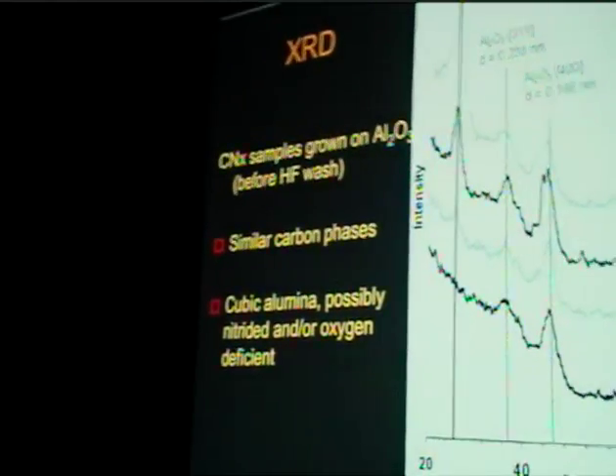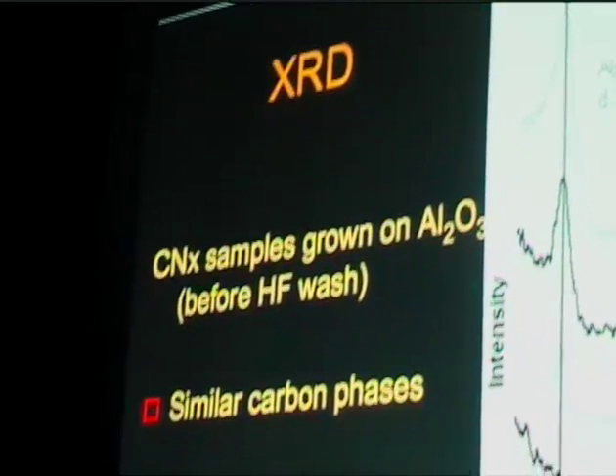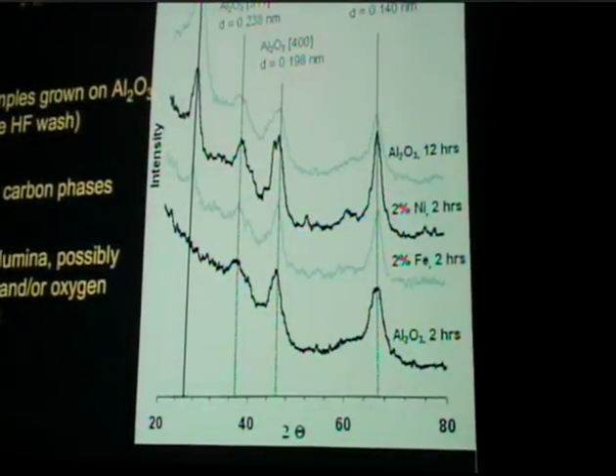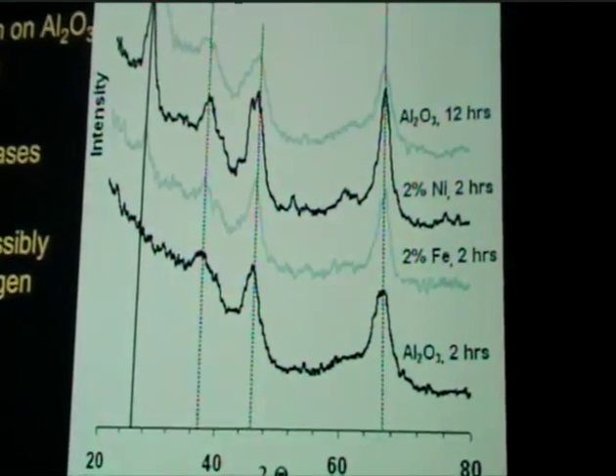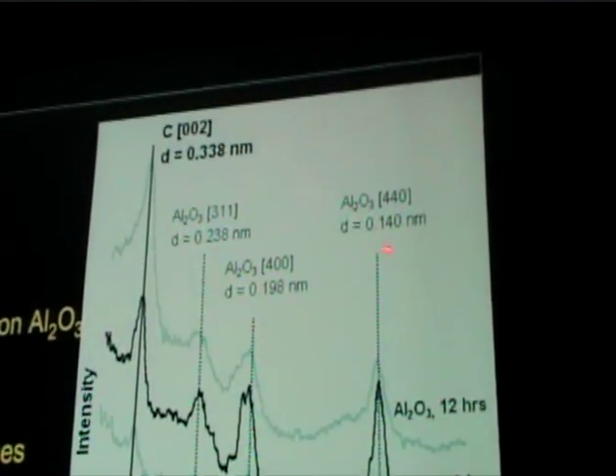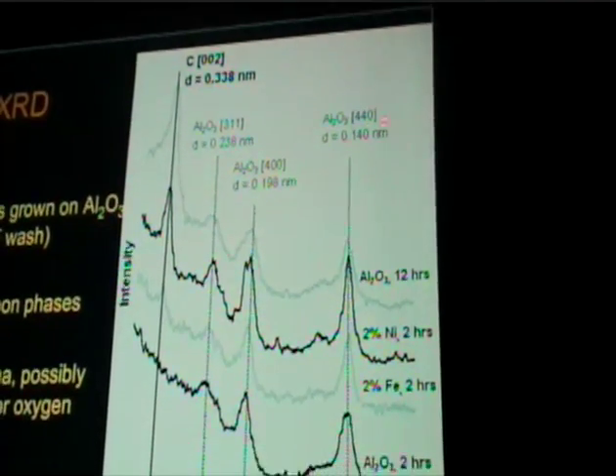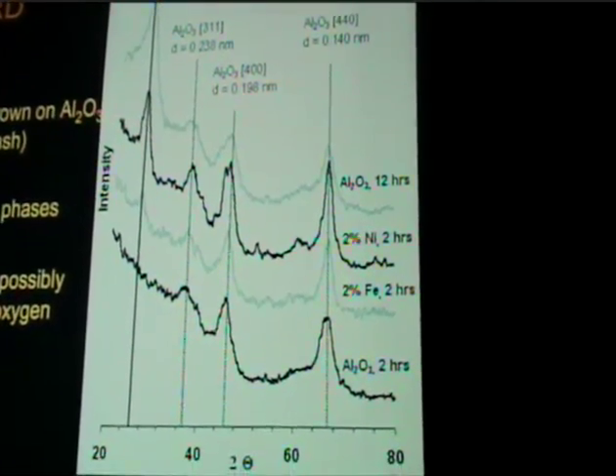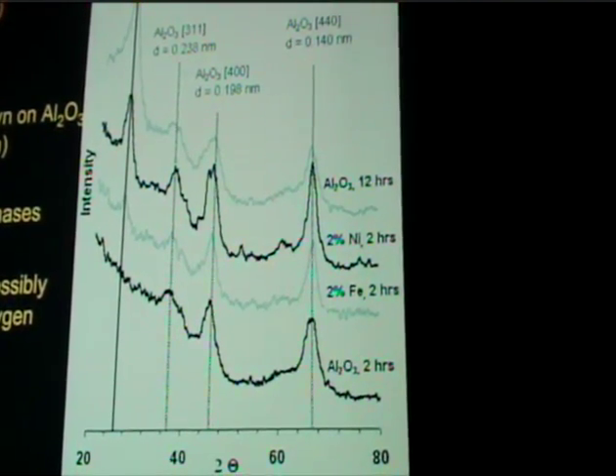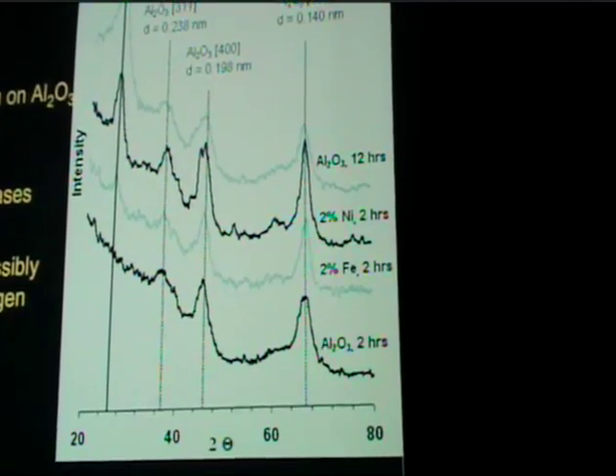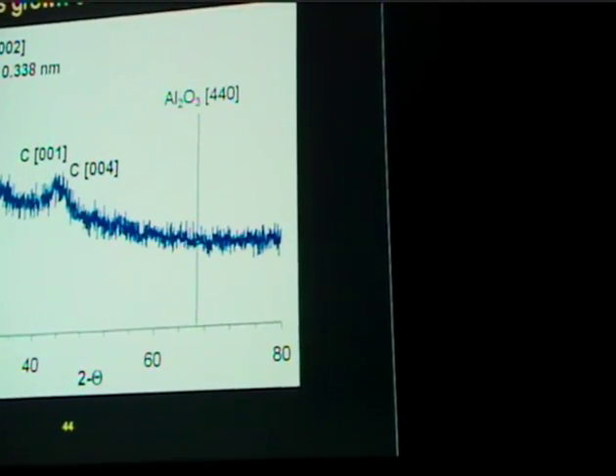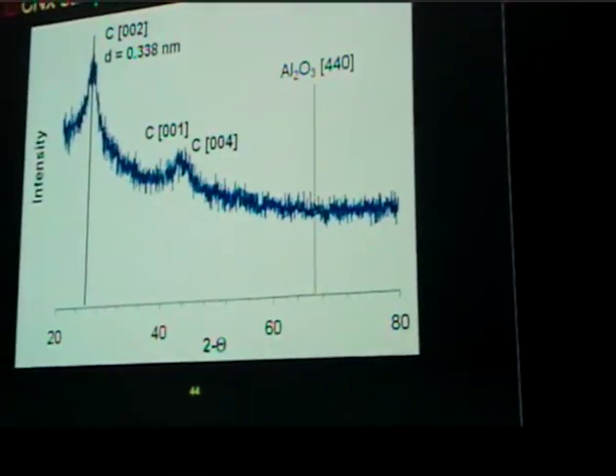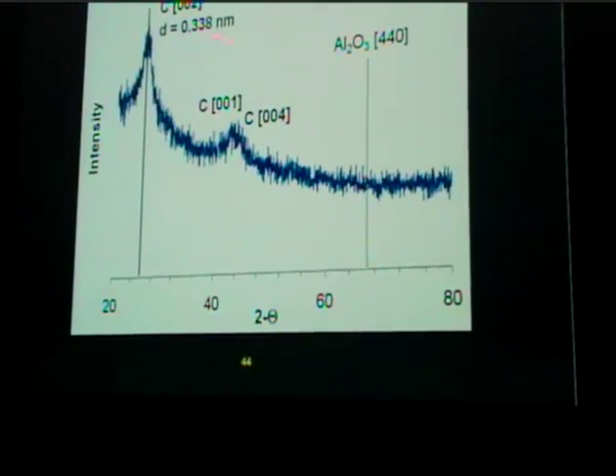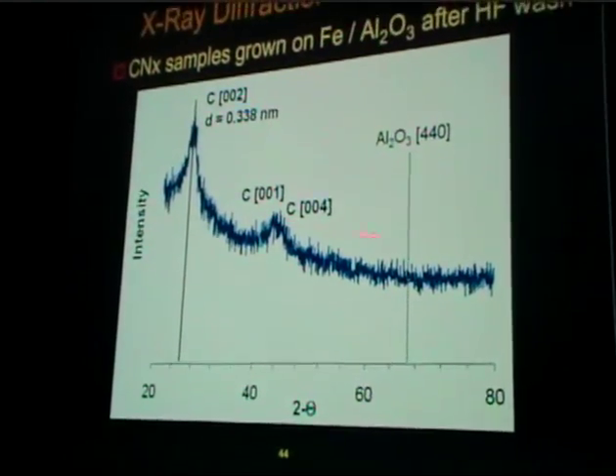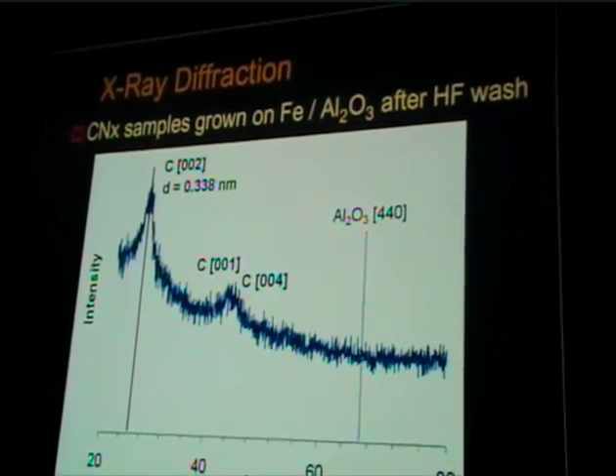Now, if we look at the X-ray diffraction patterns, these are CNX samples grown on alumina, and this is before the hydrofluoric acid washing. We see these spacings that correspond to the carbon, but we also see these spacings that correspond to alumina, but there's also some nitrided or oxygen deficient alumina as well, and we've seen evidence of this using XPS. But after washing it with hydrofluoric acid, what we see is only the diffraction lines that correspond to the graphite, and we really don't have any of the alumina left in these samples.